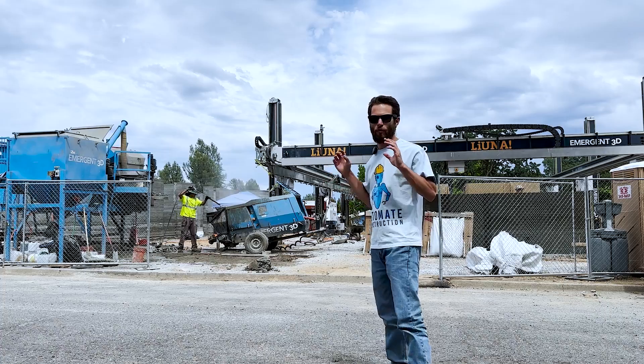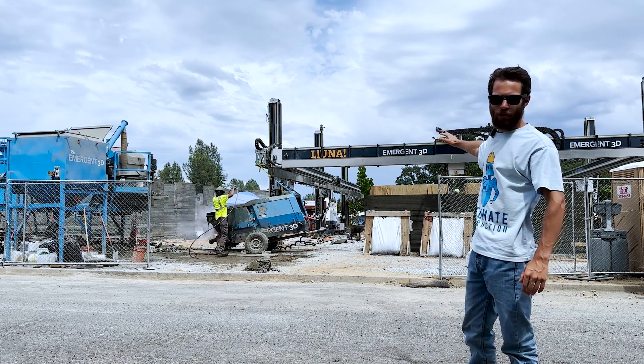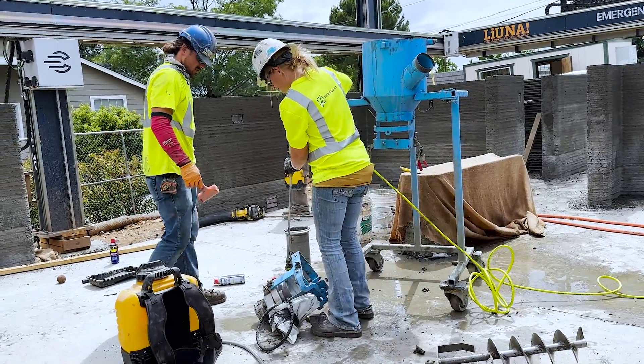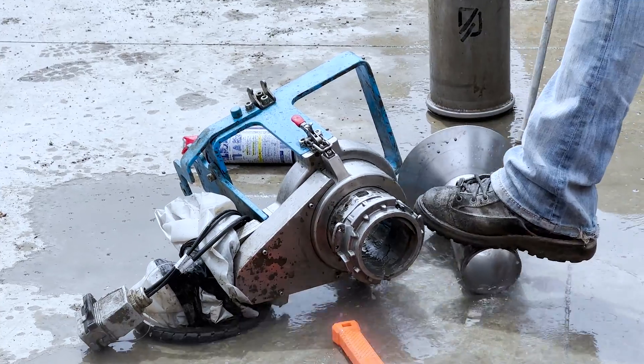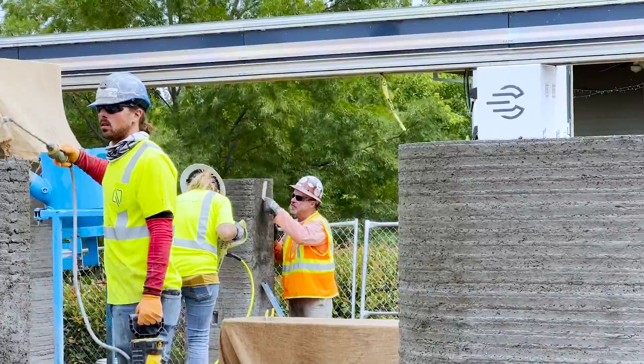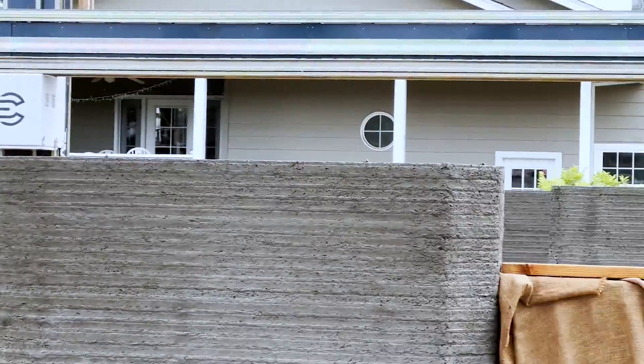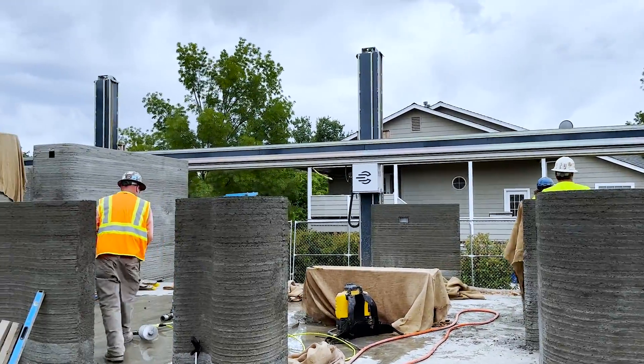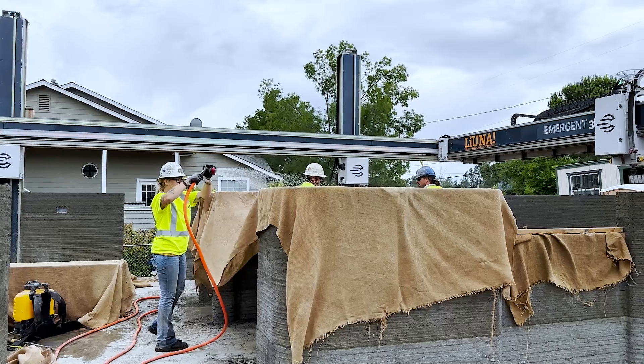To close out the print day, they give a thorough power washing to the batch plant mixer and also the extruder head, which gets dismounted from the printer. You can see the extruder head is no longer on the axis of the printer — it's being washed at the station that holds it. Steve is going around with the level making sure all of the door and window openings are straight 90-degree angles so that the install is easier. With everything cleaned up, they move the burlap from yesterday's print to today's fresh print, and continuously spray the print with water to ensure maximum humidity for minimum cracking.